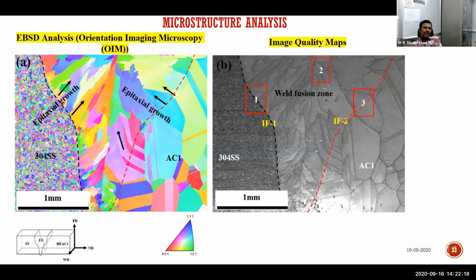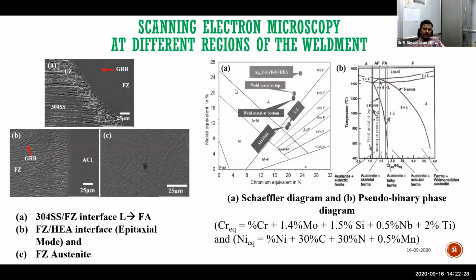It is because of the faster cooling rates associated with this electron beam. And again, we want to see what the associated interface with this system is. We have taken the Schaeffler diagram and pseudo-binary diagram of the systems, and the chromium equivalent we have taken, and we found that our system is falling in the austenitic structure only. This is the location where my AC1 is falling, and even the weld metal at the top and bottom is also falling well within the single phase FCC structure.